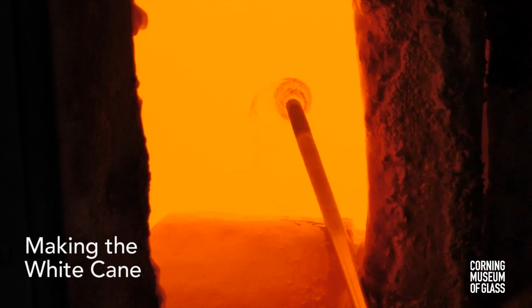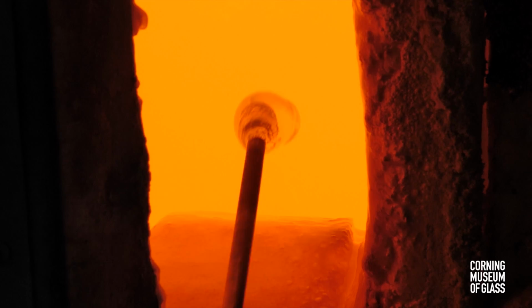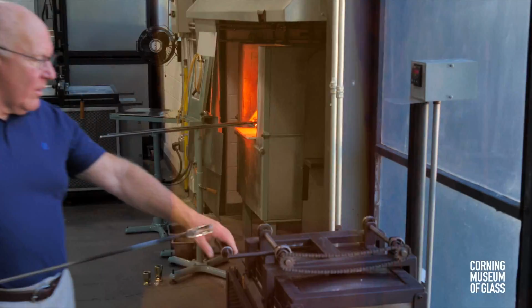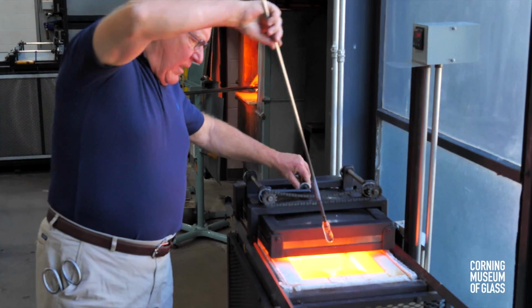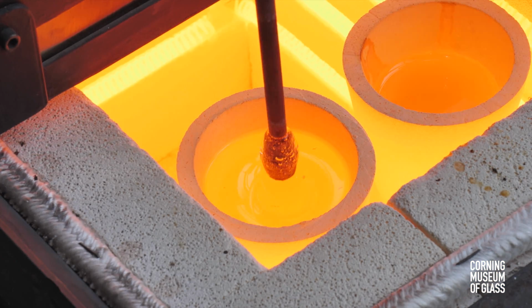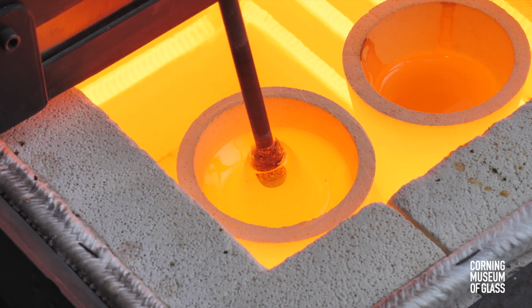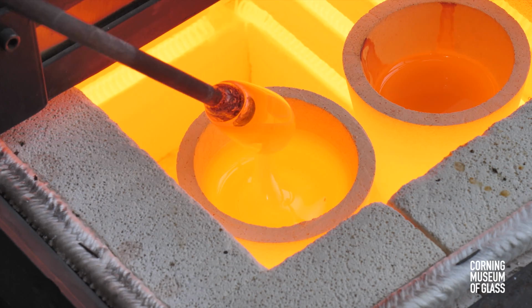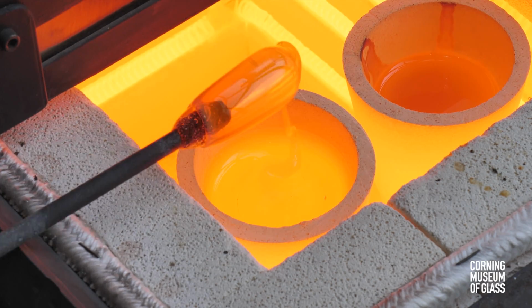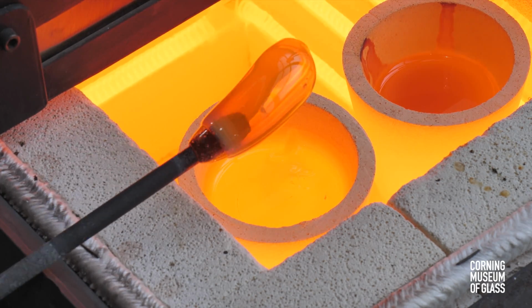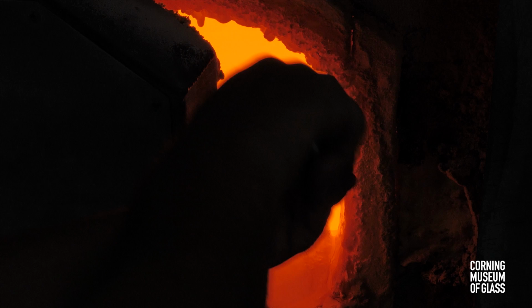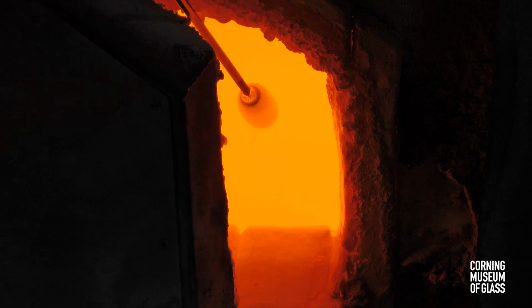The cores of the white canes are transparent glass. The cane making begins with a gather of clear glass thinly overlaid with opaque white glass, and after this solidifies, another gather of clear glass is taken. Here the layer is very thin. Excess glass is allowed to drip off into the furnace.